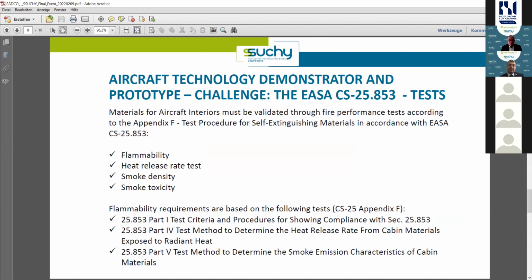What is very challenging, of course, are the EASA requirements for the certification, because all interior materials have to be self-extinguishing and fire resistant. And this is why, because we were acting in conformity with CS 25, which is for aircraft above 19 seats. And of course, we are still ongoing with the tests that are flammability, heat release rate tests, smoke density, and smoke toxicity. To qualify the material to be used in aircraft interiors, we absolutely have to fit the requirements, and the tests have to be successful. Actually, they are still ongoing.